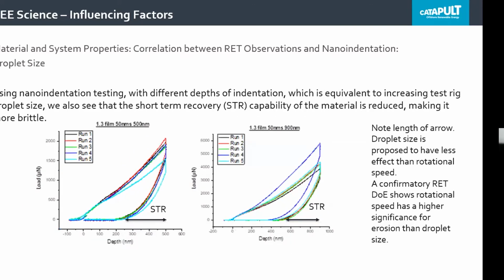Same again if we look at droplet size. In this case, what we looked at was using different depths of nano indentation, which we assume to be equivalent to changing the droplet size. And you can also see that short-term recovery, as you get to a larger, what we would call droplet size, we're seeing a lower short-term recovery value.